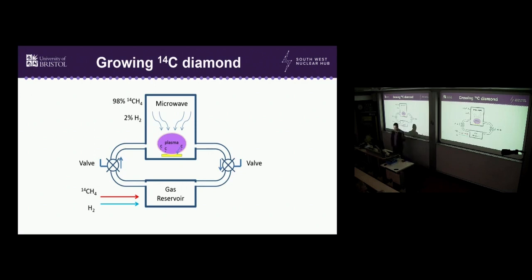We know it works. We haven't grown a carbon-14 diamond yet, partly because I haven't got all the safety cases in place. But we have grown the world's first ever isotopically pure carbon-13 diamond. And that's actually a diamond which is harder than diamond. You may be surprised to know. And that's because actually the atoms are just a little bit closer together. And because the atoms are a little bit closer together, it makes the diamond much harder. And that's potentially very, very useful for the oil and gas industry for digging holes. Because you've got something which is not only harder, but it's got a higher thermal conductivity than normal diamond, which is recognized as having basically the highest thermal conductivity you could have of any material. So on its own, that's quite revolutionary, I would say.